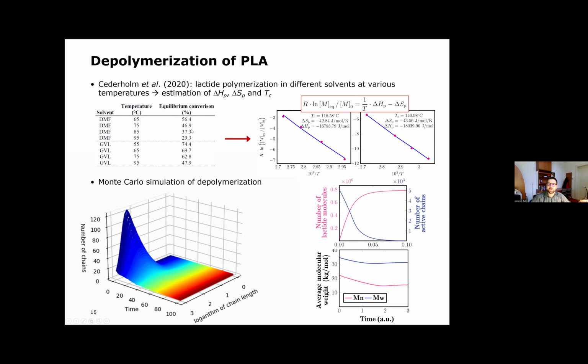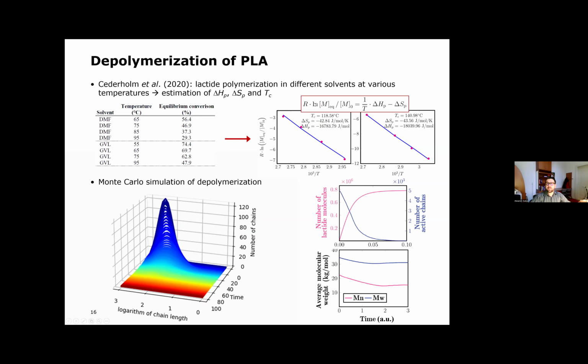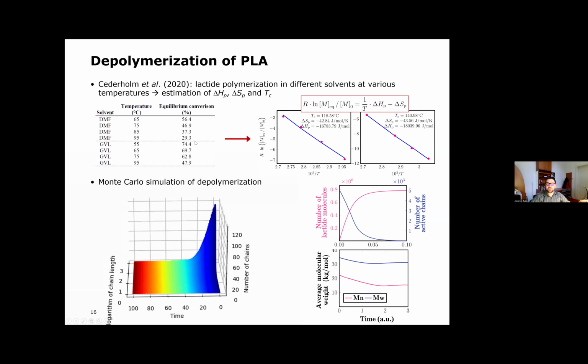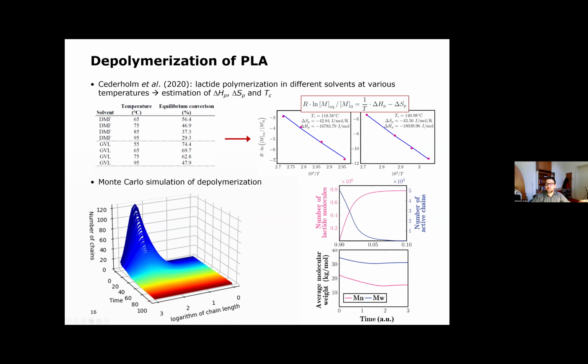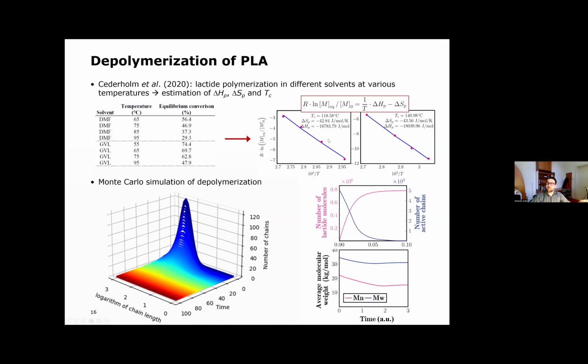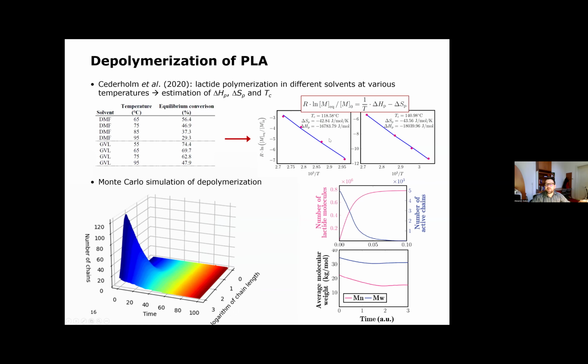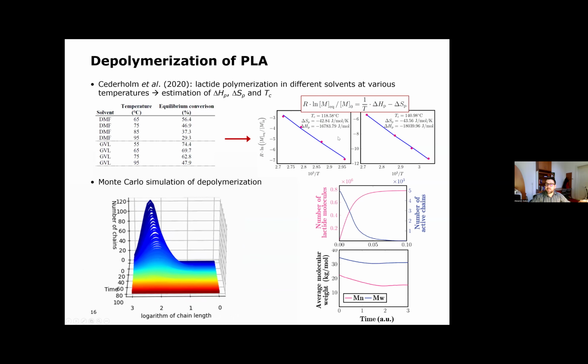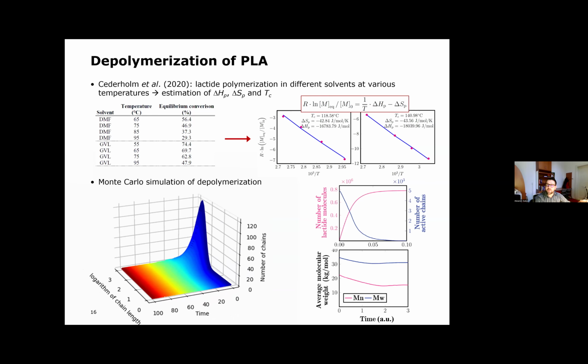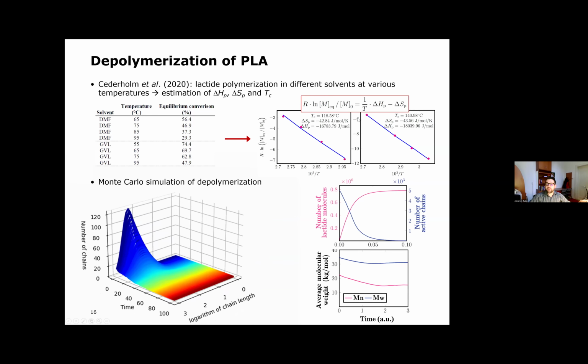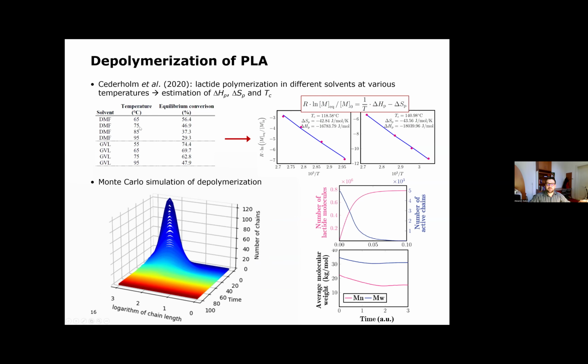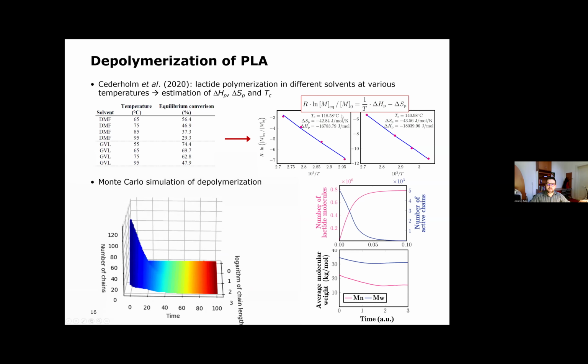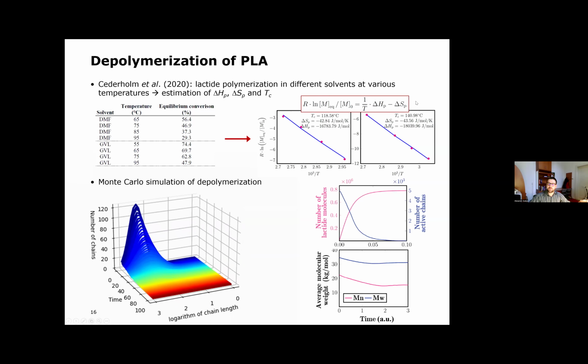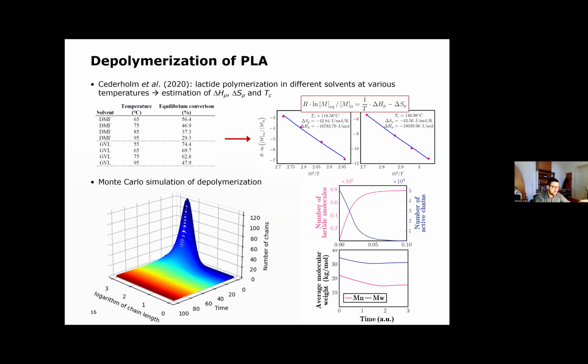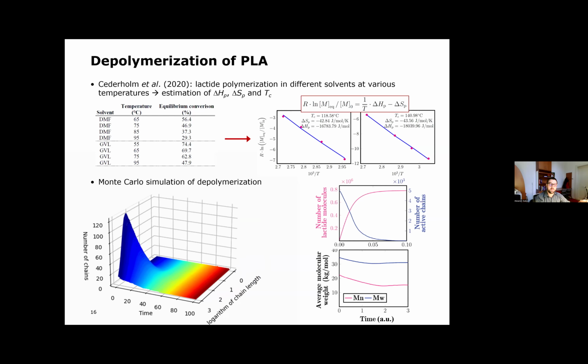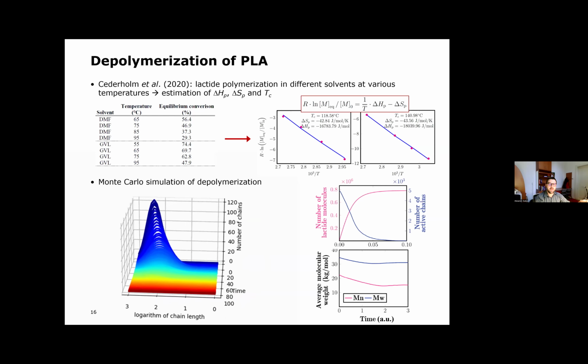That is basically translated to the monomer equilibrium concentration. So this Dainton equation actually can be linearized, and these two sets of data for two different solvents can be put into a graph. Using linear regression of this linearized data, you can easily estimate the entropy and enthalpy of the polymerization as well as the ceiling temperature. And you see that these different solvents lead to dramatically decreased ceiling temperatures of 120 and 140 degrees Celsius, which is something that might be really used, we hope, industrially in reality.